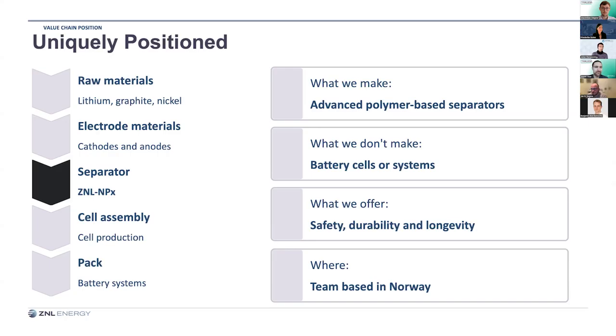Yes, so basically, if you want higher nickel in a high nickel NMC, the higher the nickel content you have, then you will have nickel shuttling or manganese migration from one side. So you're poisoning the battery. Since we are non-porous and tight, you don't have that nickel shuttling effect or the migration of the manganese. So you can have it, because the goal in an NMC is to have as low as possible on the cobalt side because of the ethical part and the mines in Congo, and of course the manganese. Same with lithium sulfur. So we are enabling the battery cell manufacturers to have higher nickel or lithium sulfur or high voltage on sodium. Okay, gotcha.